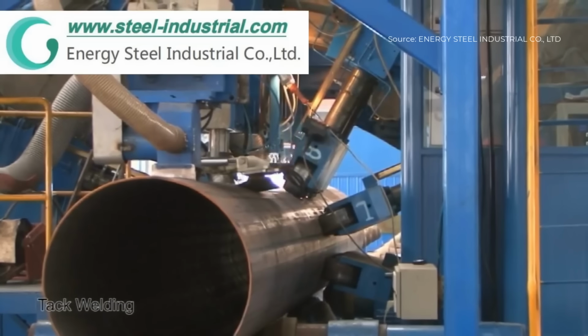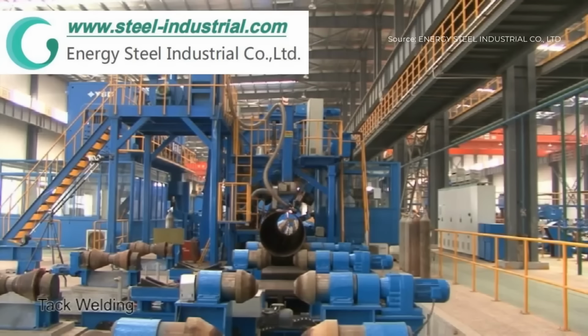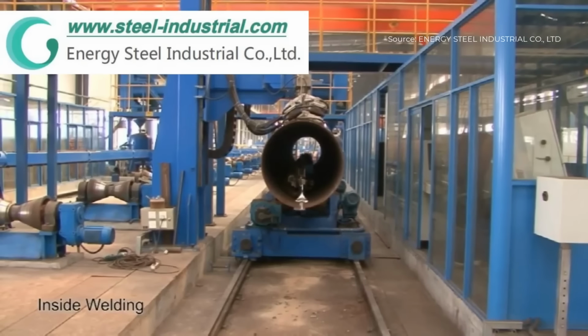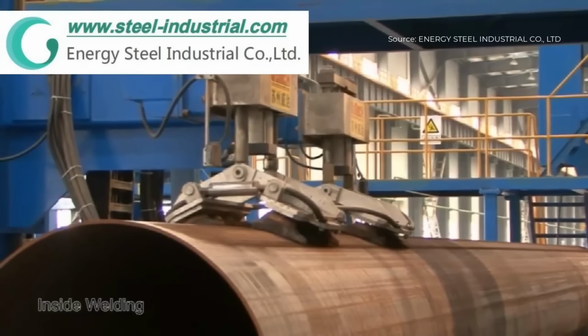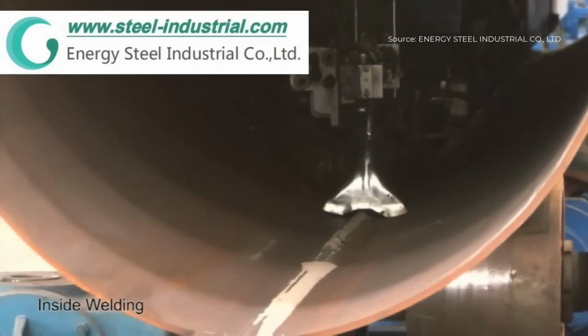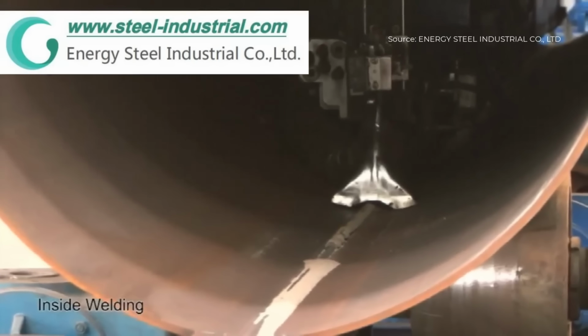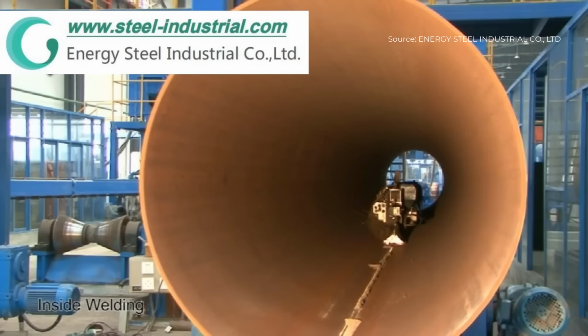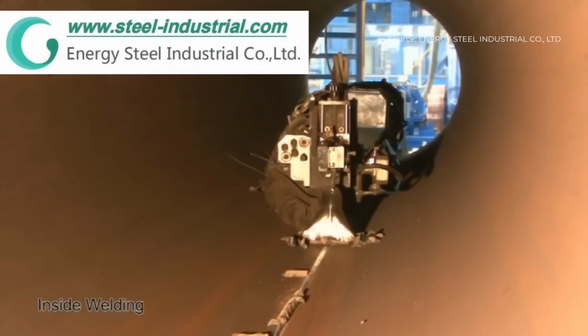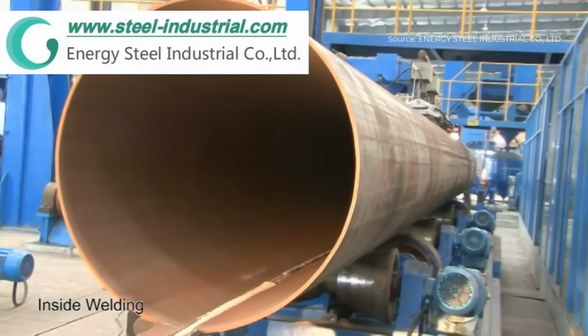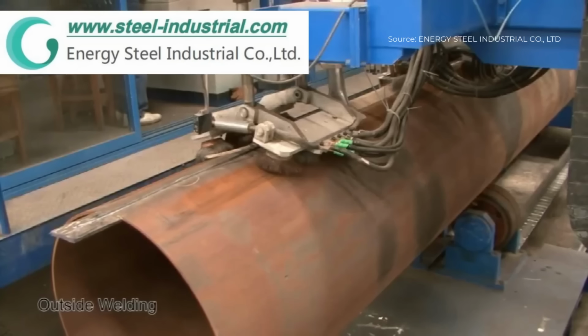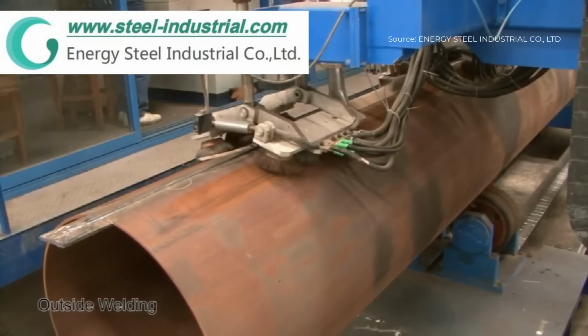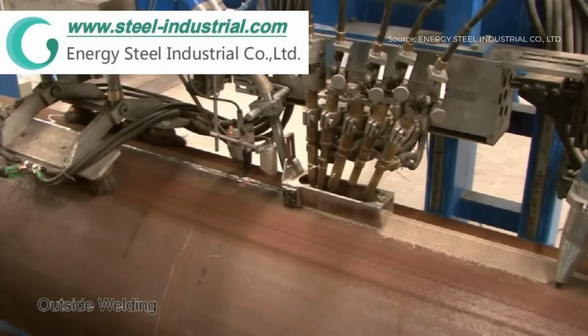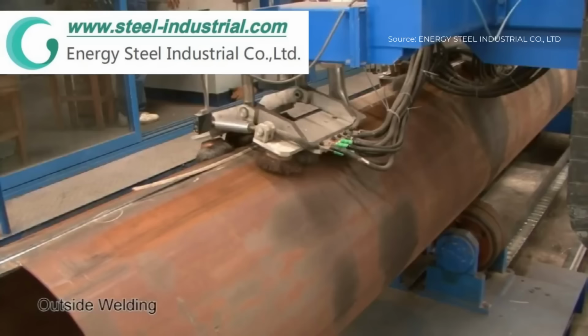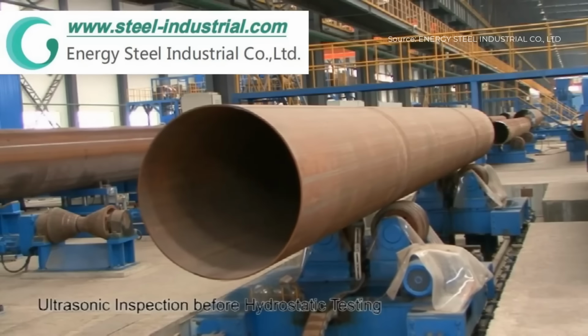Tack welding is applied along the open seam to maintain the pipe shape before final welding. Inside submerged arc welding is then performed on the longitudinal seam. The welding head remains fixed to ensure stable welding parameters, accurate control of weld quality, and continuous recording of welding data. After the inner seam is completed, outside submerged arc welding is carried out along the same longitudinal joint, also with a fixed welding head to ensure consistency and traceability.